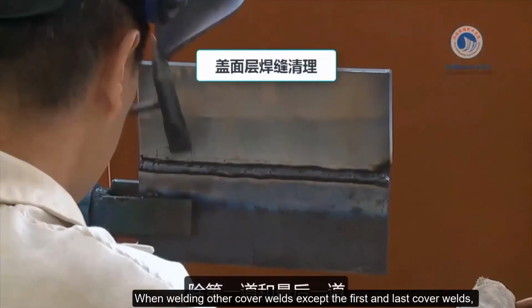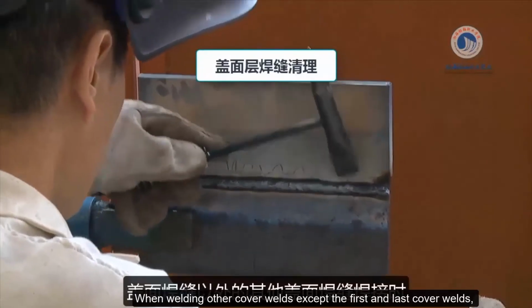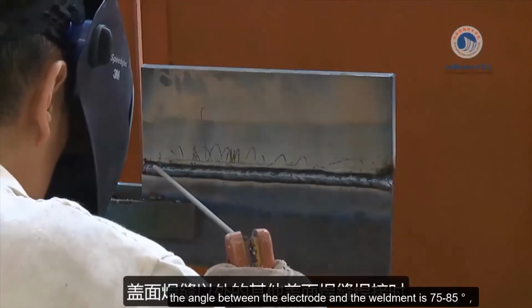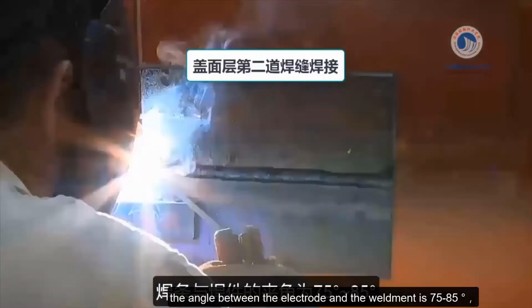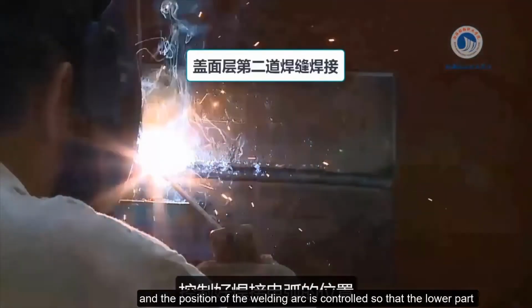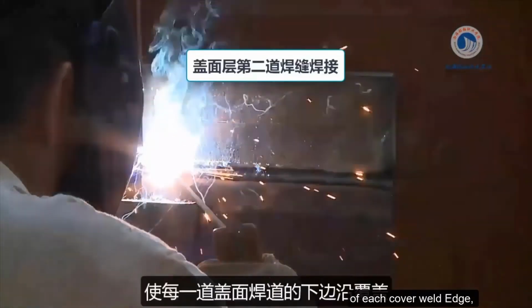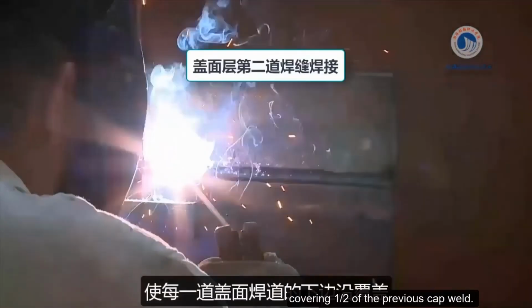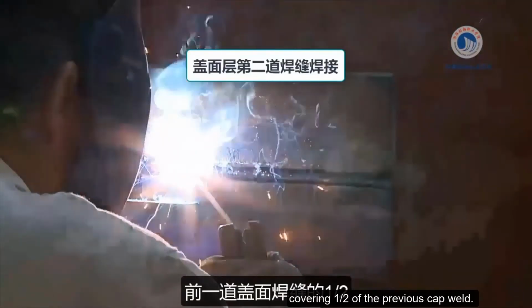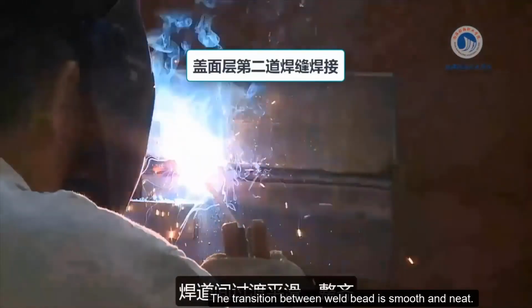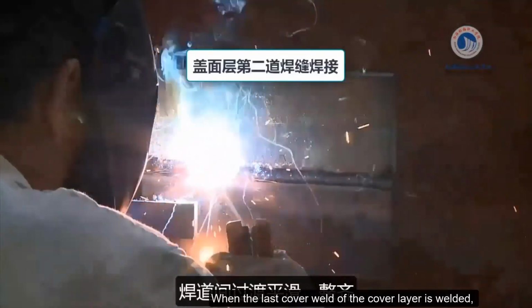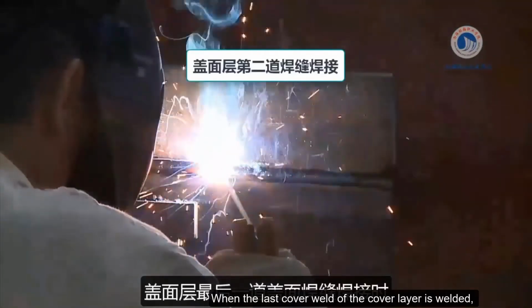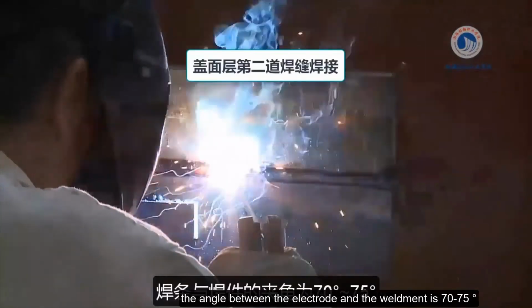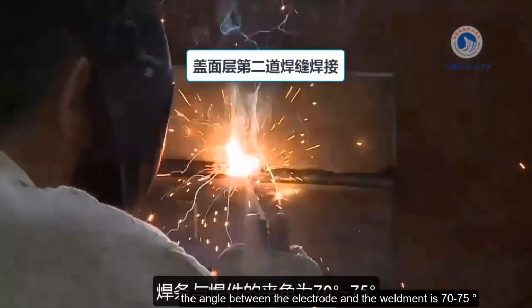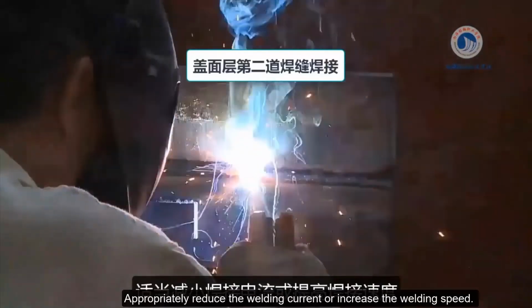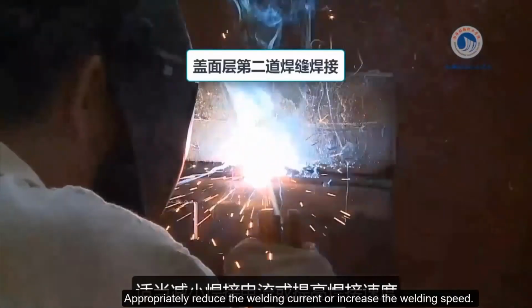When welding other cover welds except the first and last cover welds, the angle between the electrode and the weldment is 75 to 85 degrees, and the position of the welding arc is controlled so that the lower part of each cover weld edge covers 1/2 of the previous cap weld. The transition between weld beads is smooth and neat. When the last cover weld of the cover layer is welded, the angle between the electrode and the weldment is 70 to 75 degrees. Appropriately reduce the welding current or increase the welding speed.